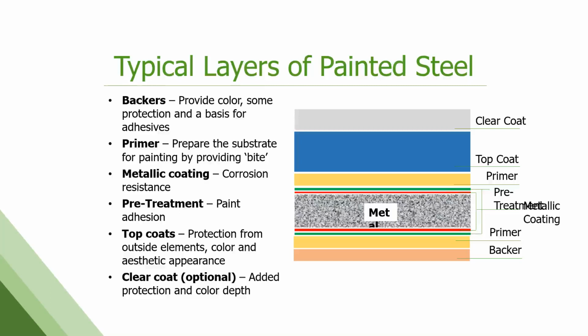While the focus today is going to be on paint, I do want to talk a little bit about the whole system here for reference. Here's a cross-section of what we've got. You've got base steel or aluminum, which is your substrate. If it's steel, there's almost always a metallic coating on top of that for corrosion protection. Then we put down the pre-treatment on both sides. That helps etch the surface and prepare it to take the paint.